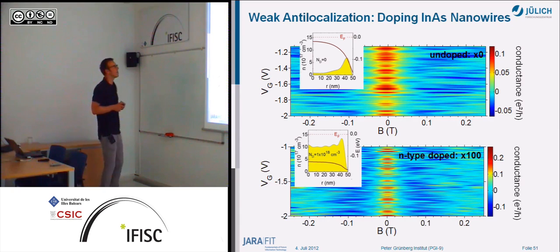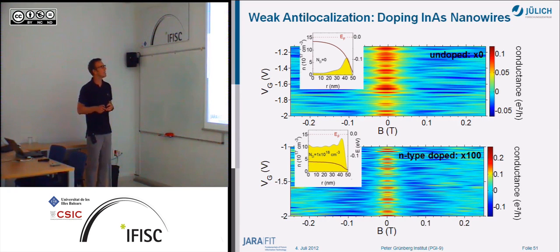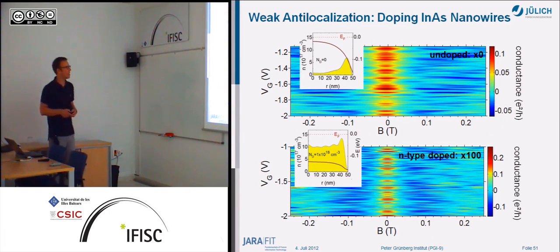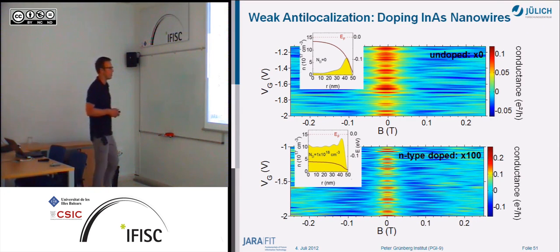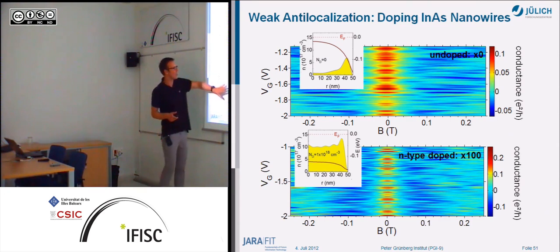What we're currently working on is looking at indium arsenide nanowires, and we ask ourselves how strong the weak anti-localization is in indium arsenide if you have different doping. Yeah? For instance, if you have no doping, you have a surface electron gas, so you would expect a strong potential gradient here, while if we have a largely doped nanowire, then we can maybe expect a smaller spin-orbit coupling. Now that's our current work here.